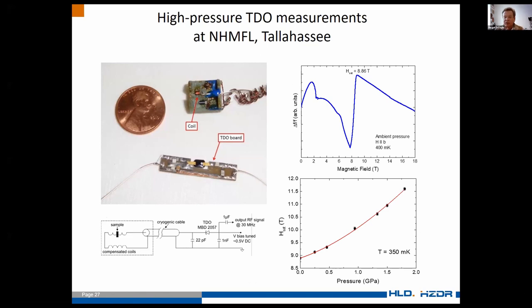We use a tunneling diode oscillator. This is something which measures magnetization or susceptibility at radio frequency. The sample is stored here, in a very small coil of several tens of turns. Once we sweep the magnetic field, and magnetic parameters, for instance permeability, change in the sample because of a phase transition, we can see this as a change of the frequency.